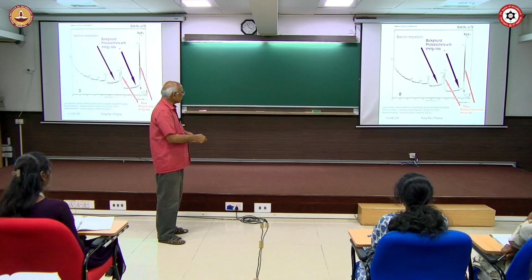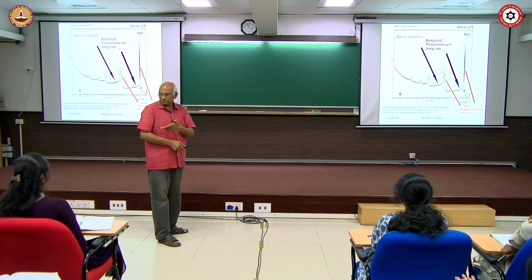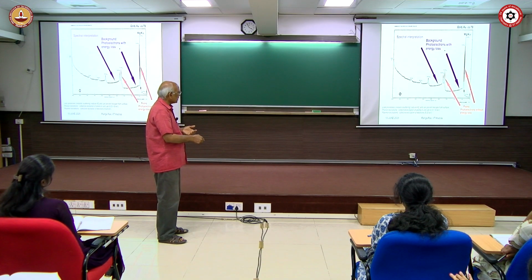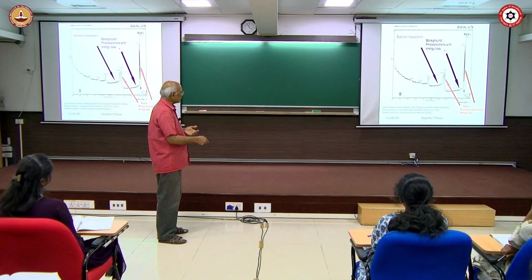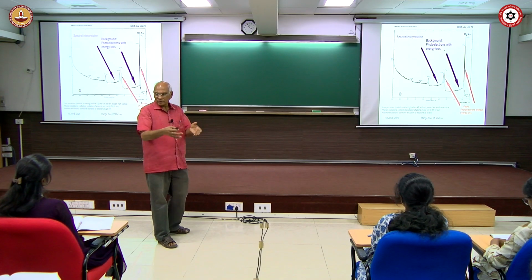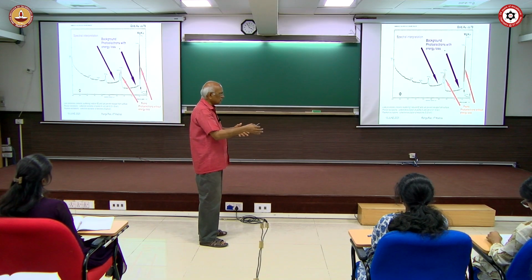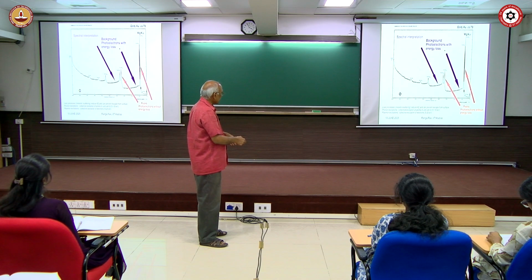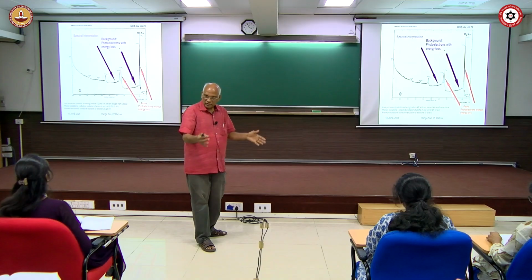The losses are because of inelastic scattering, as I said. Loss processes include inelastic scattering, which can prevent escape from the surface, then phonon excitations, a phonon being nothing but a collective excitation of atoms, where some energy is lost to the phonons, and plasmon excitations, a collective excitation of the electrons, where some electrons get excited.